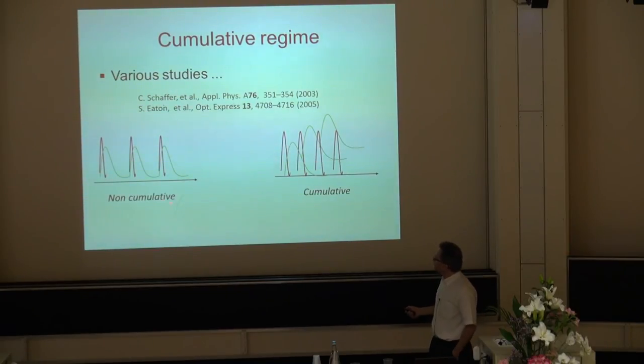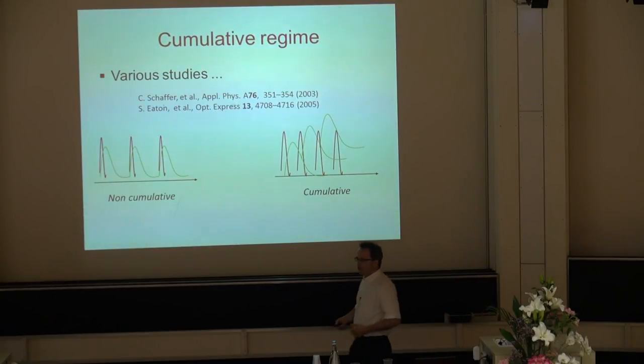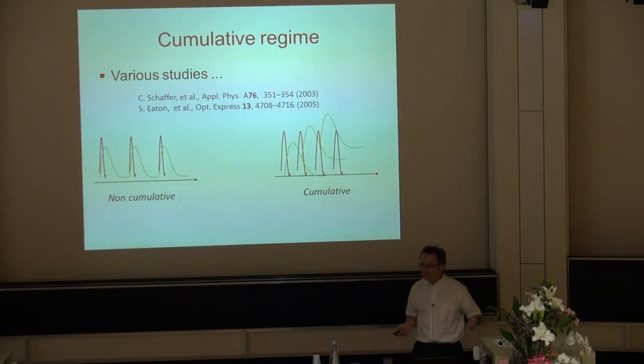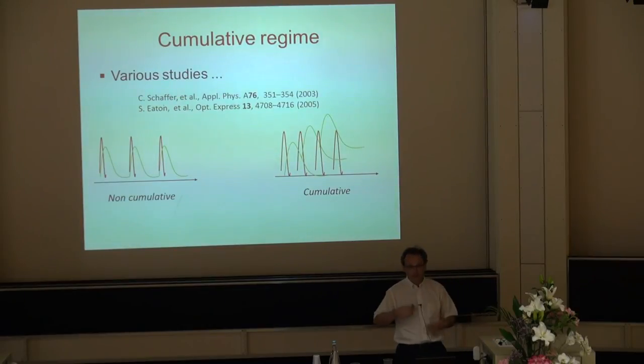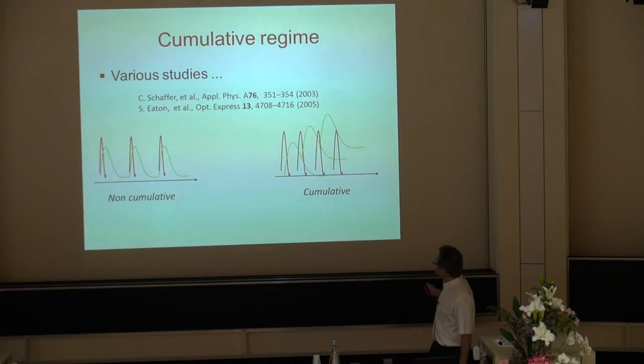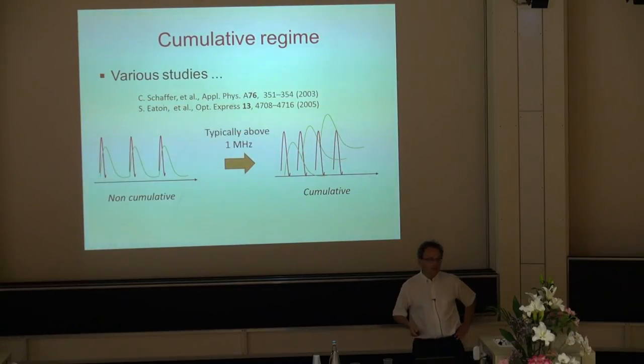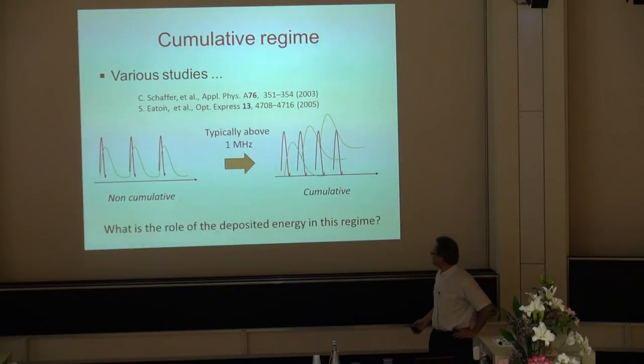That can be understood like this: imagine this is my laser beam, and now this is the material response. If I give enough time for the material to get back to a rest position, then it doesn't matter how far apart my pulses are. Now if I put them very close to one another, I'm not giving any time to the material to come to rest. So you have a cumulative effect. And that's typically above a megahertz, when you fire the pulses very, very often.